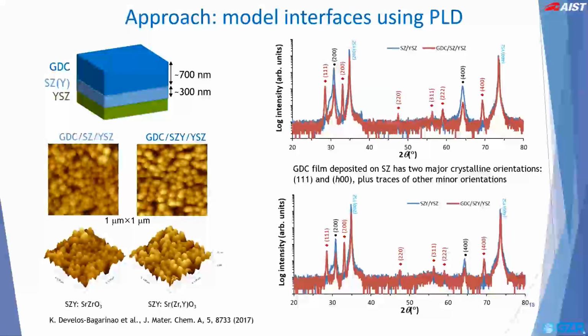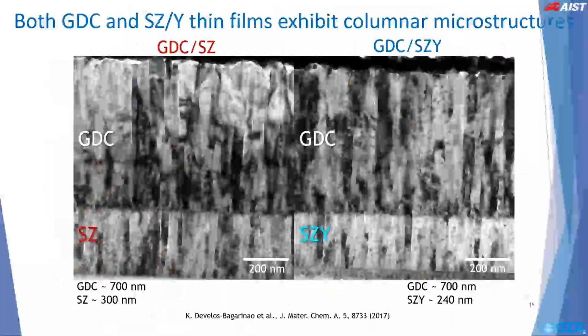The slide shows some representative AFM images and XRD patterns showing the multilayers of GDC and strontium zirconate prepared on YSZ. The films are highly crystalline and have dominant orientations, which are influenced by the YSZ single crystal substrate orientation. This slide shows typical cross-sectional TEM images obtained for the two types of heterostructures.